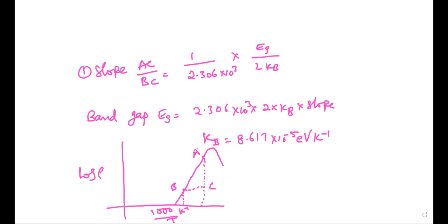So the resistivity of the germanium crystal is a function of inverse temperature. For this sample, when T is less than T dash, in degrees Kelvin, in this region, which is one region, conductivity is mainly due to the impurity carriers.